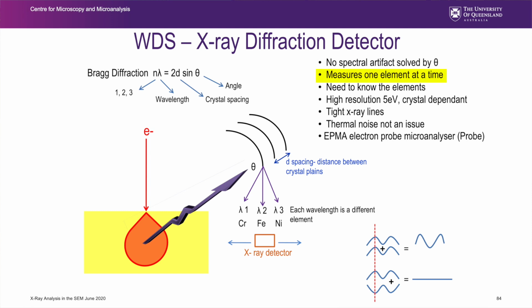It's slow, you've got to do one element at a time, but you get very good spectral resolution. Why? Because if you recall, when you get waves, they can constructively or destructively interfere. When you're on the peak, they constructively interfere and you get a strong peak. As soon as you go off the peak, you get destructive interference, and you get a very flat background. So that's how the microprobe works. And because of that, you've got very high spectral resolution and low background, and that gives better accuracy, better detection limits. But it's one element at a time, and you've got to measure the backgrounds independently. I actually say to calibrate a WDS spectrometer, I need 30 minutes per element. As you begin to add elements to your analysis, it really adds up on the calibration.